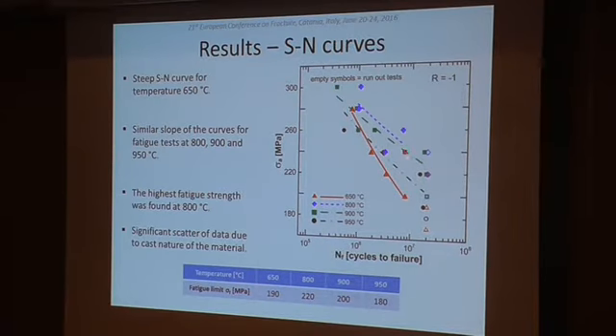The other three temperatures had already similar slope of these curves, and we observed just a slight decrease of fatigue properties with increasing temperature. The best fatigue performance was measured at temperature 800 centigrades, which is also highlighted by the highest fatigue limit. The significant scatter of experimental data is given by the cast nature of the material with coarse structure.